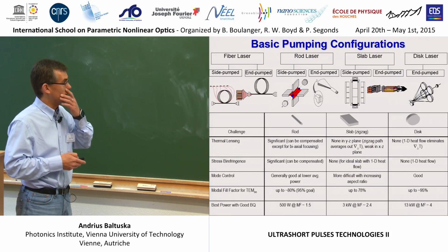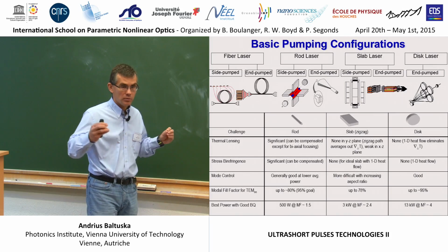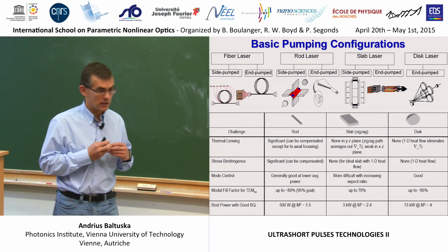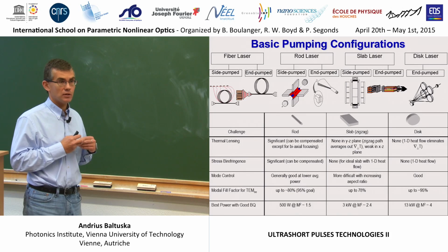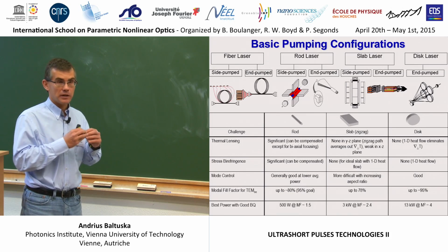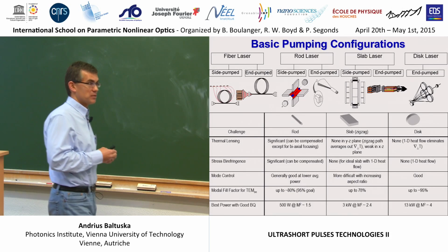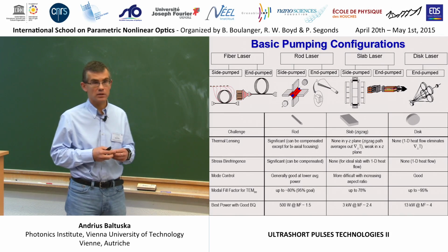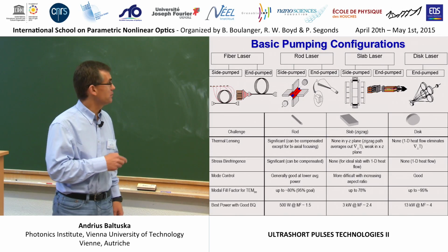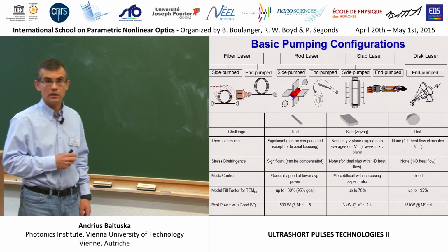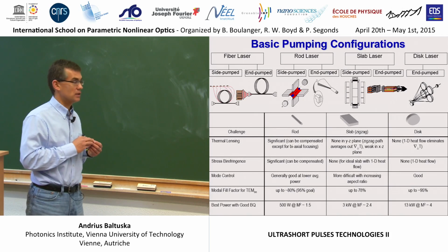Okay, and the technology has diversified itself in terms of the geometry. So one of the biggest problems for high power lasers is heat extraction. So you're trying to optimize geometry in such a way that you have a large surface area to extract your heat from. And compounding problems are thermally induced birefringence, also the buildup of this B integral. So for instance, we can take the fiber arrangement and it has a beautiful surface area, but then we would have an extremely long propagation length.